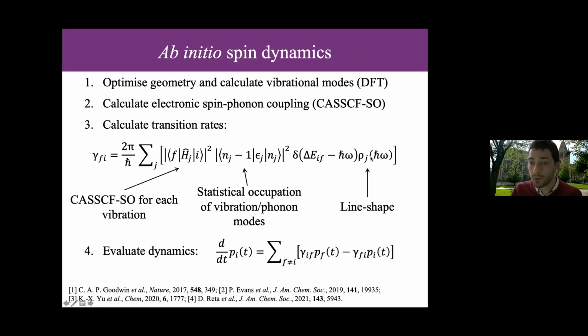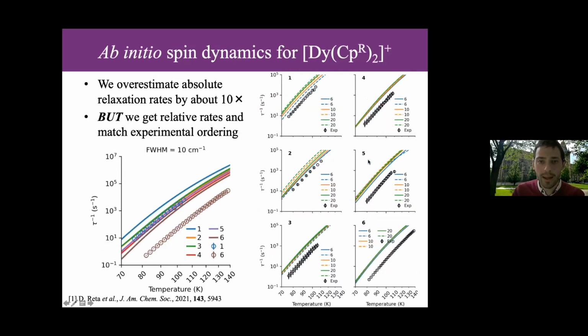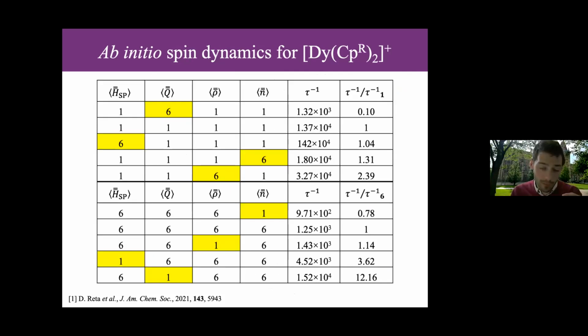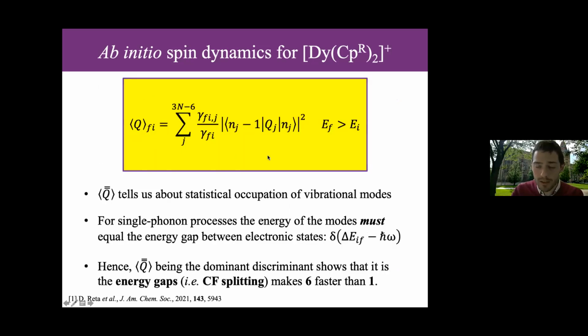And it is this term here that tells you how close is this chosen h bar omega to your actual vibrational mode, J. Okay. So we're always using the energy gaps of our vibrational mode, which are the same as the electronic energy states. And so when we find that this Q term is dominant, that tells us that it's because the energy gaps are larger. That is, by using the occupation term from the Layfield molecule, it slows down relaxation because the occupation of the higher energy vibrational states is lower than in the worst dysprosium single molecule magnet. And that occurs because the energy spacings of the crystal field states are bigger in Layfield's compound than they are in the worst dysprosium single molecule magnet.